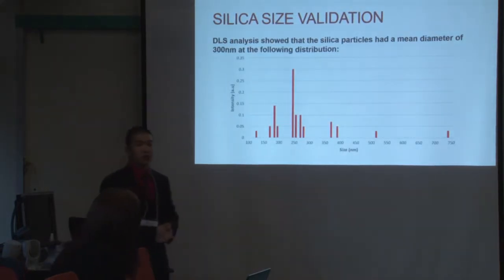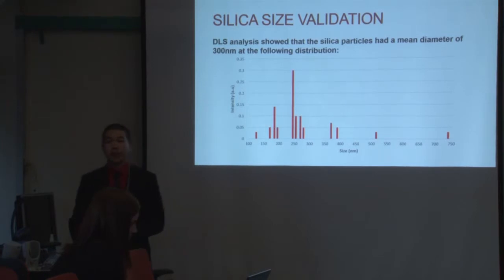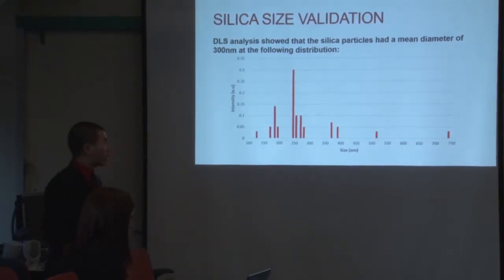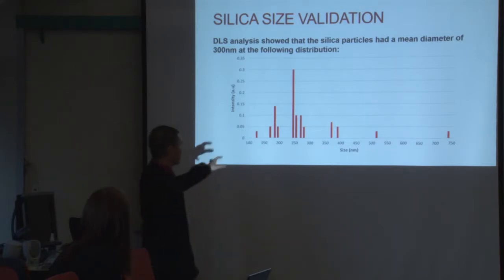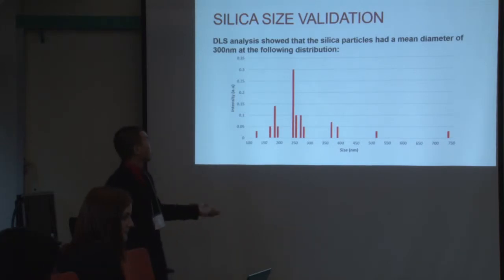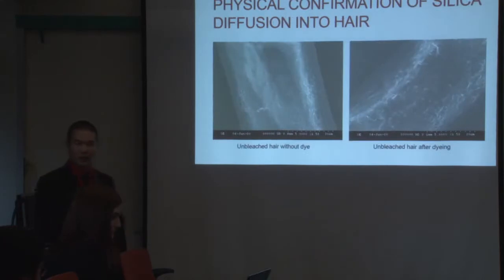So we also used dynamic light scattering to validate our particle size of about 300 nanometers. As you can see here, the particle distribution is actually very nice. It's centered around 250, but the mean diameter of our particles was found to be 300 nanometers, not meters.